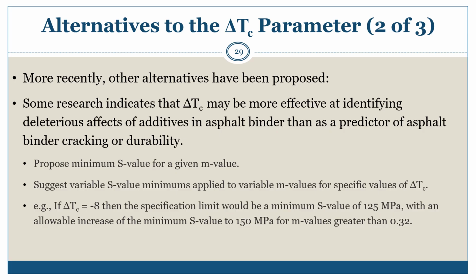For example, if delta TC is minus 8 degrees C, then the specification limit would be a minimum S value of 125 megapascal with an allowable increase of the minimum S value to 150 megapascal for M values greater than 0.32. Considering these observations of the delta TC parameter's functionality to identify deleterious additives, it is understandable that the delta TC parameter could be used to identify presence of non-bituminous asphalt binder components. However, more straightforward methods of restricting use of unwanted asphalt binder additives are possible.